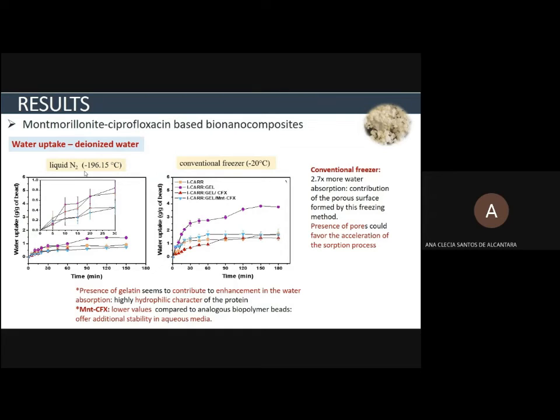Also observed is that the beads containing montmorillonite-ciprofloxacin show lower values compared to the analogous biopolymer beads, which indicates that these systems based on the intercalation compound offer additional stability in aqueous media. When comparing these bionanocomposite systems in their different freezing methods, it's observed that those submitted to conventional freezing showed higher values of water uptake in pure water, which can be attributed to the porous surface formed by the conventional freezing method.